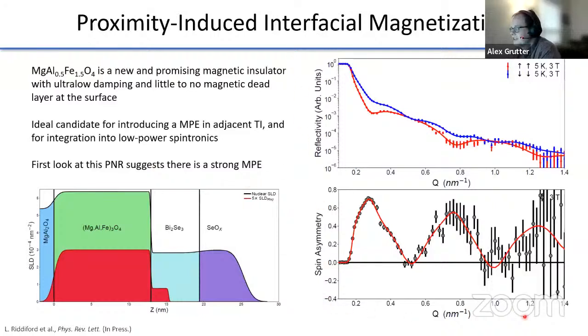We take neutron reflectometry measurements, we fit them, as you can see in the solid lines. I would argue this is a pretty good fit to the data. And so intrinsically, you just sort of say, well, that fit is really good, we should just believe what it tells us. Spoiler alert, that's probably not true. And so what we see is in the magnesium aluminum ferrite layer, you have a nice uniform magnetization. And in the bismuth selenide layer, you have a little bump right here.